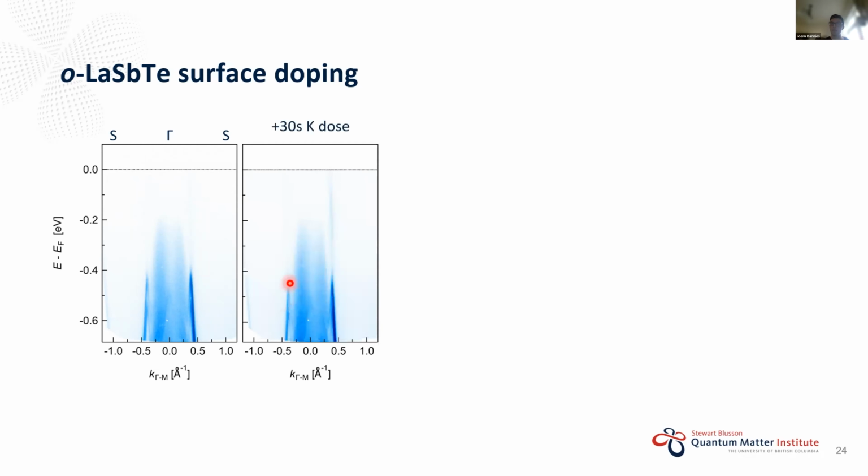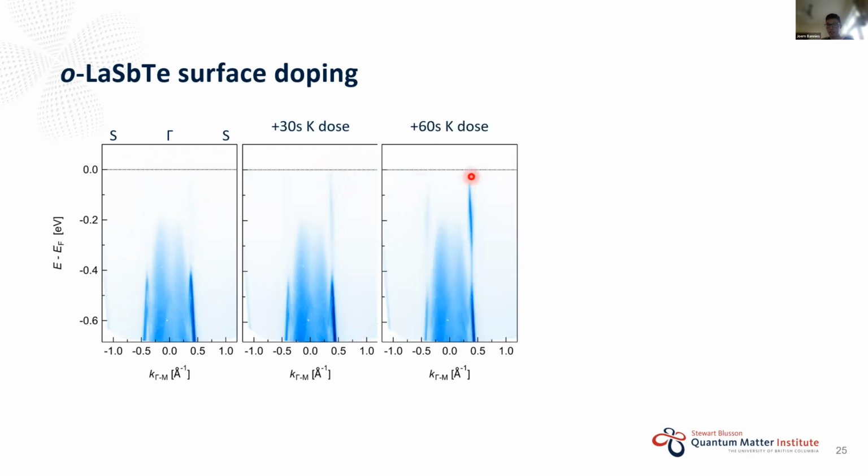And if we do this on a very short time scale, we open this shutter, we do this procedure for 30 seconds, you can already see a clear change in the band structure where this faint conduction band is coming down now, so the gap is shrinking. If we repeat this step multiple times, you can see now the features even becoming more clear.